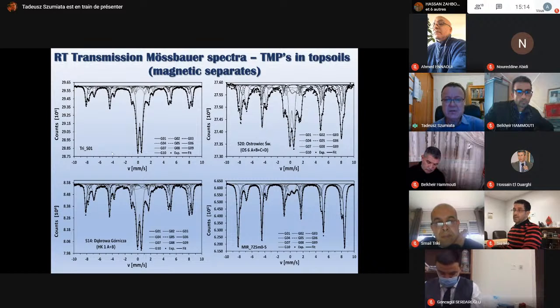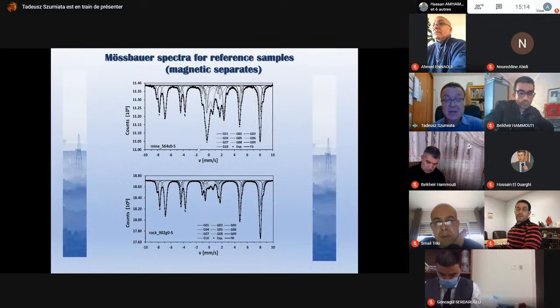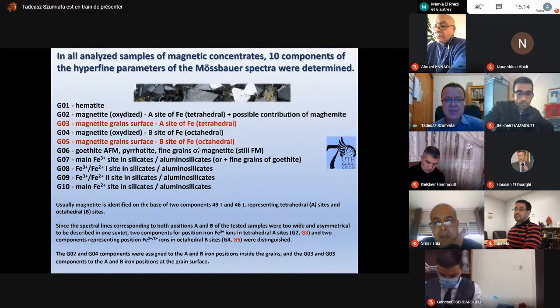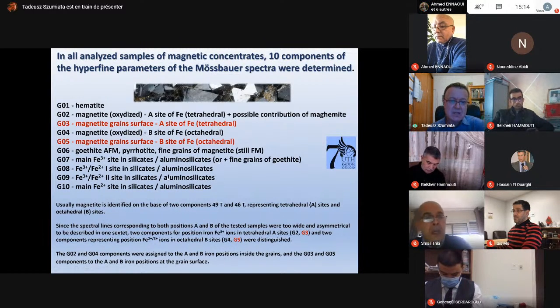And we also made Mössbauer measurements for these 2 reference natural samples. What we can find in the samples: we can see hematite, we can see components from magnetite, a small amount of goethite, and still quite huge amounts of aluminosilicates, which are of natural origin, of soil background origin, but not of our interest.